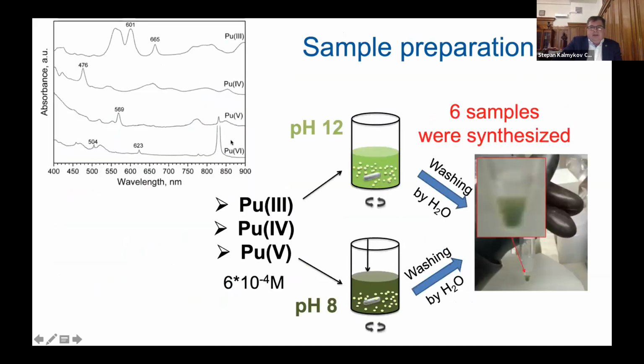The experiment was done in many different conditions, in many different ways, at different pHs, and also on different time scales, when we took different precursors. So we took plutonium-3, plutonium-4, plutonium-5, and plutonium-3, 4, and 5 separately. Then in a relatively acidic range, we increase the pH, and we can see the precipitate that is formed quite fast. And we wash this precipitate, and then we analyze it through different spectroscopic and microscopic methods.